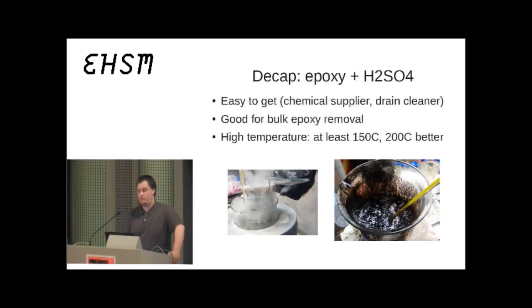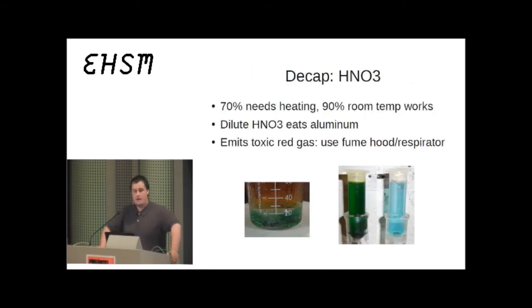Because the problem you can see over here is that this solution turns very, very black. You can't see through it at all. You have no idea by visual inspection if the chip is done. One way you can mitigate this, though, as far as the fumes, is you could just let it cool down and hope for the best. But you will get some problems. If you put a chip in too long, you'll tend to actually corrode it a little bit, which I'll show a little bit later. The other really common technique is using nitric acid.